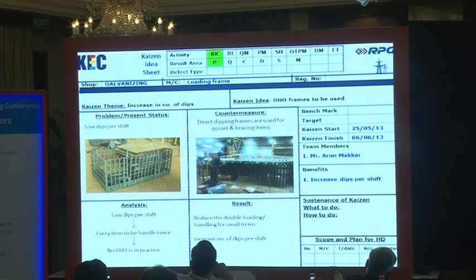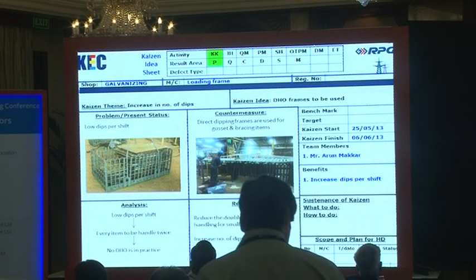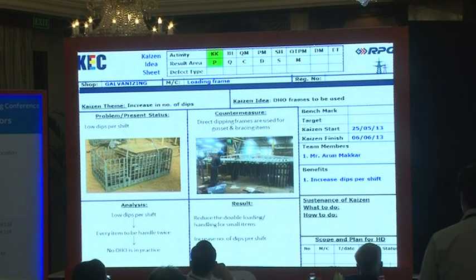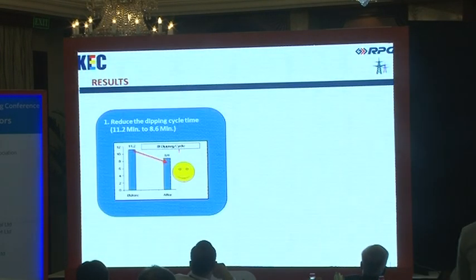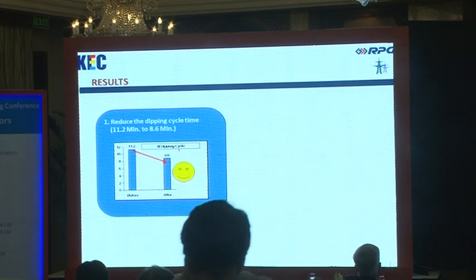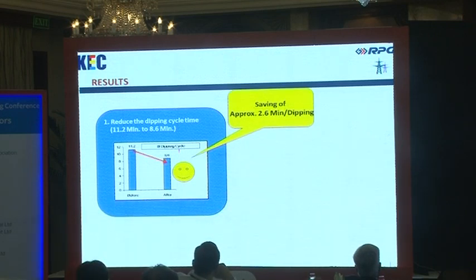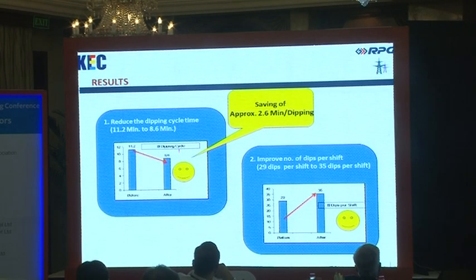So for that, as per the recommendation of the IZA, we are designing new frames so that we can optimize the maximum bath, as well as in the galvanizing, the variation of the temperature is mitigated. So with uniform dipping, all the material is inserted in the bath at the same time, at the same level of temperature.